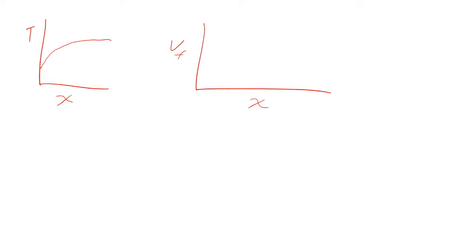And it asks us to relate that to free volume, which we know as things cool at a faster rate, we have far more free volume, and as things cool slower, we have less. So we figured we'd have some sort of sigmoid curve in which you have a surface free volume at a maximum, and then it would peter out to the bulk, as when it was completely cooled.